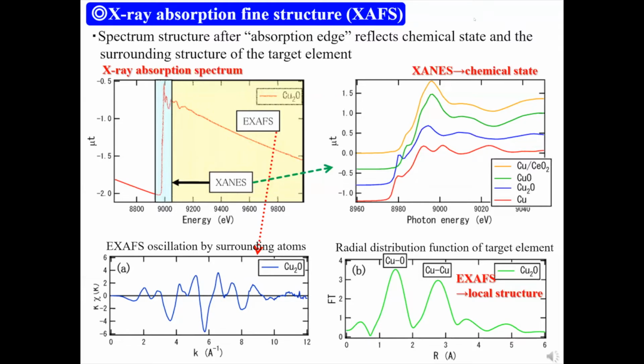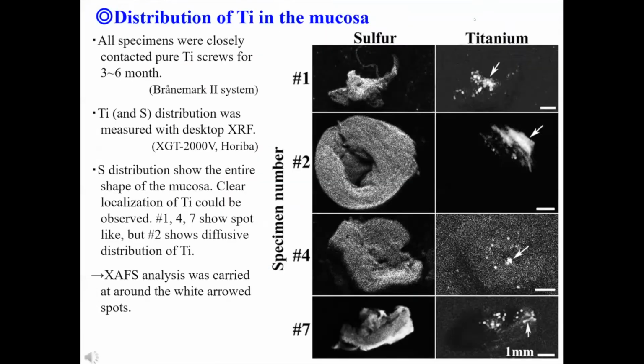We applied this near-edge spectroscopy for the chemical state analysis of titanium in mucosa. The tested mucosa was in contact with the titanium cover screw for 3 to 6 months. Therefore, titanium was accumulated in the tissues as shown in those images. X-ray absorption analysis was carried out around the white arrowed spots to reveal the state of titanium.